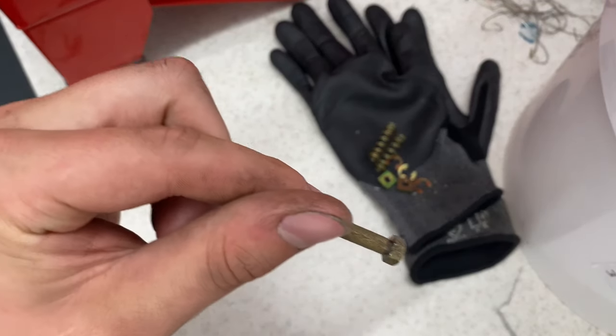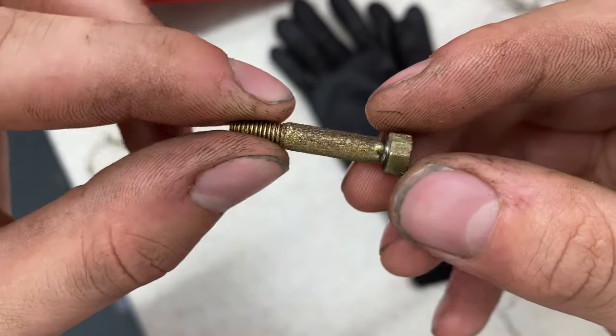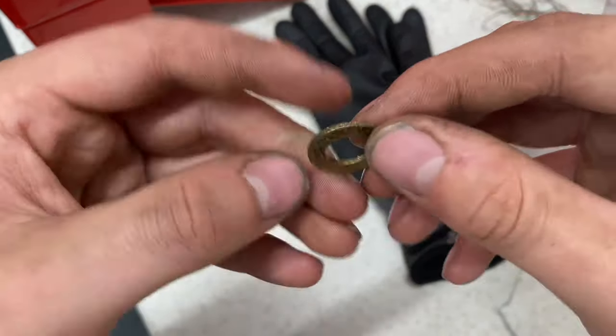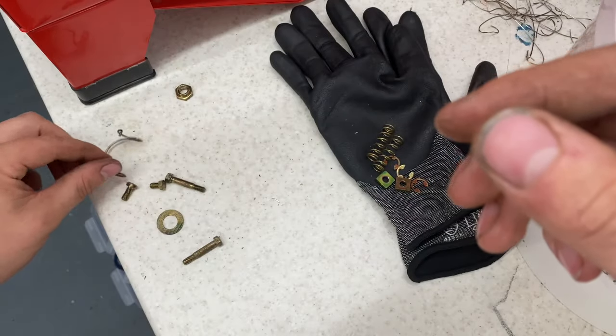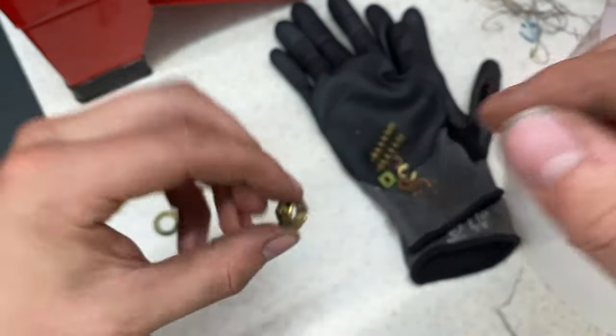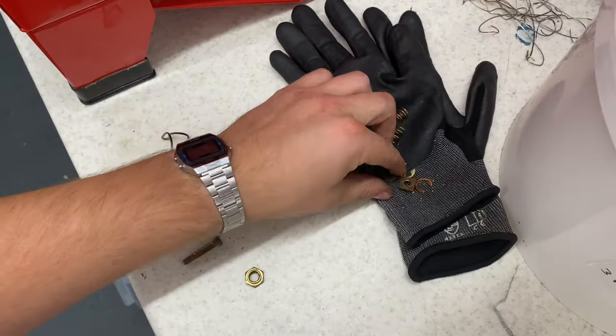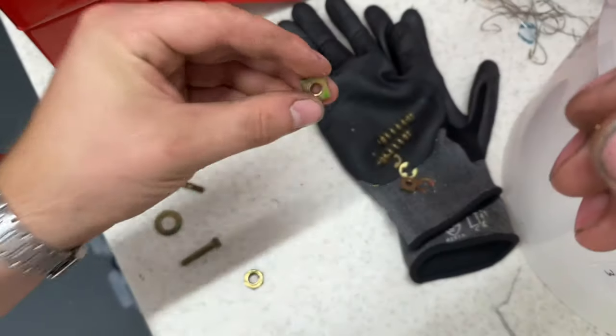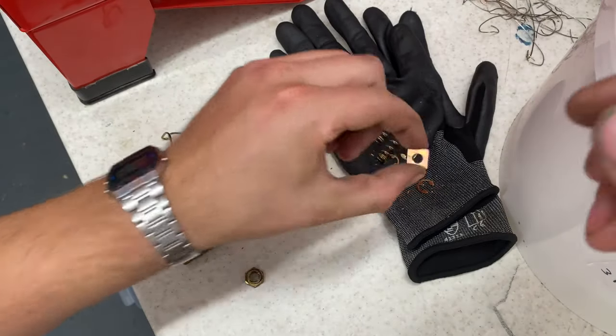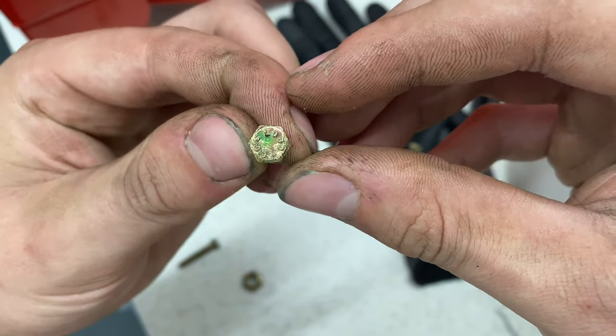Unfortunately there have been instances where it's gone a bit wrong. One part went wrong first, I tried to replate it, but unfortunately the threads are so damaged they'll have to be replaced. There have been quite a few over time. Luckily these are things I've discovered and now plan to change. Before most of this work I wasn't using the muriatic acid, the sand blaster, or the wire wheel as much — so with these it's a much improved process and I'm really not getting that many faults.